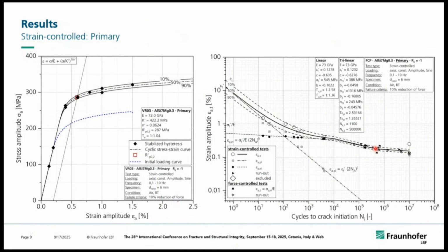In this area, and additionally we included also the points from the stress control test from the unnotched specimens in this evaluation to get it a bit more stable, especially in this area. Beyond 10 to the power 5 cycles, we can state that we have more or less a pure linear elastic material behavior, and so strain and stress differ only by the Young's modulus. And so we used those test results here for a better and more substantial evaluation.